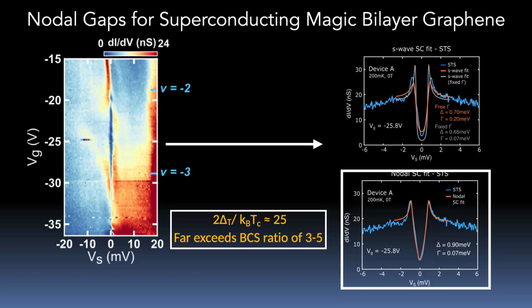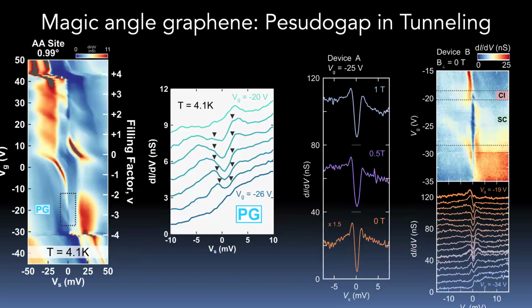Does this gap survive above the superconducting temperature? Good question. Next slide. It does. So it does have a pseudogap-like behavior. As you go up, this is at 4 Kelvin, you can kind of still see it. This is in the gate range where you have the gap at low temperature.